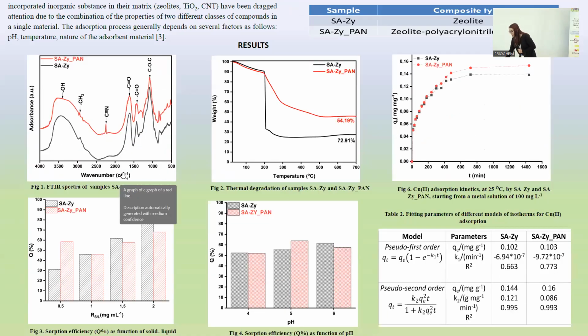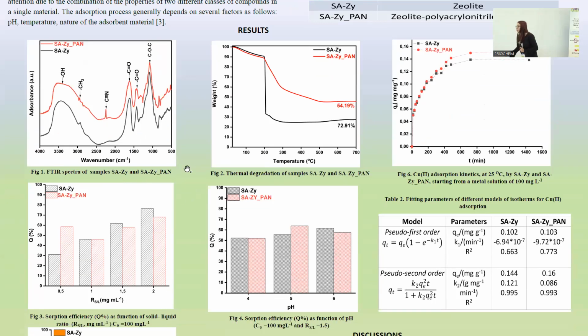To attest the capacity of the absorption of the sample, it's necessary to have the preliminary test. The first one is the solid liquid ratio, and the second one is the pH test. So we can see in this graph the best solid liquid ratio was 1.5 and the best pH was 5.